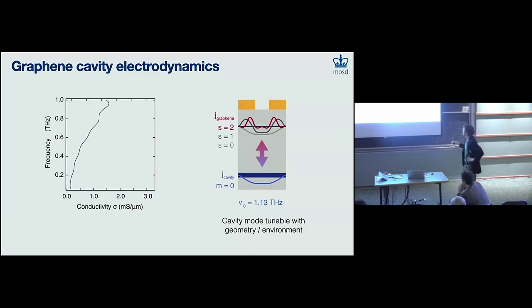So this is the measurement we get. This is with the graphene. Oh, and this is also the backgate, so we can shuffle charges between the two and tune the Fermi level. So this is what we get when the graphene is tuned to charge neutrality. And so this is the rising edge, frequencies on this axis now, conductivities on this axis. So this is the rising edge of the graphene plasmon, which should be peaking somewhere over here. That's sigma 1. This is sigma 1. We also have sigma 2, but I'm only showing sigma 1 here.